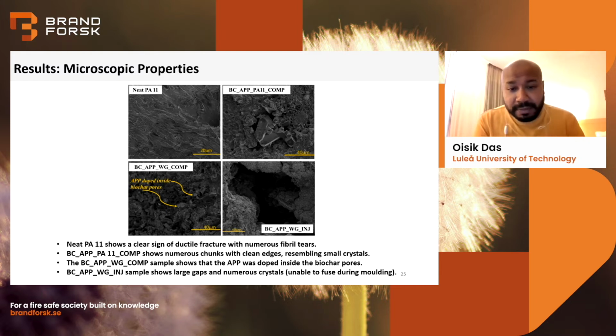Now, the biochar with APP in gluten made by compression molding was quite good. We can see the APP doped inside the pores of the biochar as intended. But when the same sample was tried to be made by injection molding, we see large gaps and ridges, which means it did not fuse together. And that is the reason it was not able to be formed.